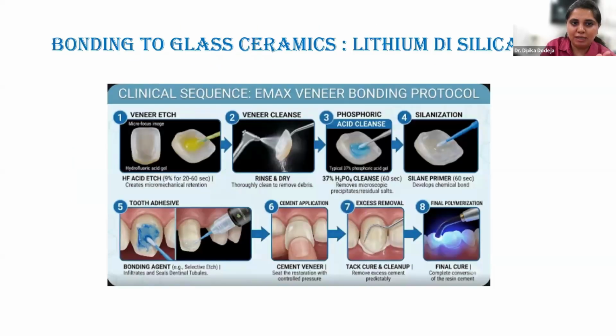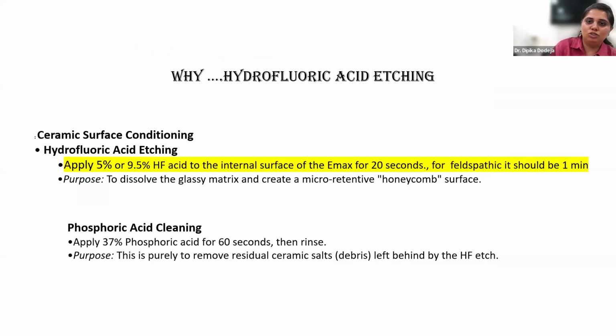Okay, the first step is hydrofluoric acid etching. 9.5% hydrofluoric acid is used for 20 seconds on Emax restorations to dissolve the glass particles from the surface and create a micro retentive honeycomb surface. Okay, either you can use a 5% or a 9.5% for 20 seconds. Over etching again will lead to the weakening of the ceramic. Okay, so we need to strictly stick to 20 seconds of hydrofluoric acid etching.